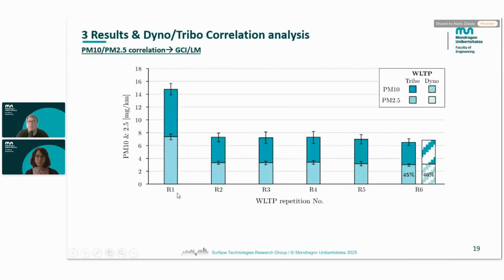Again, we also have to consider that there is a bedding process here. So in the first repetition we have quite a large amount of particle emission. However, in the subsequent repetitions we have really stable values, and in the sixth repetition, where the measurement is performed officially in the GTR, we obtain quite similar results, less than 10% difference